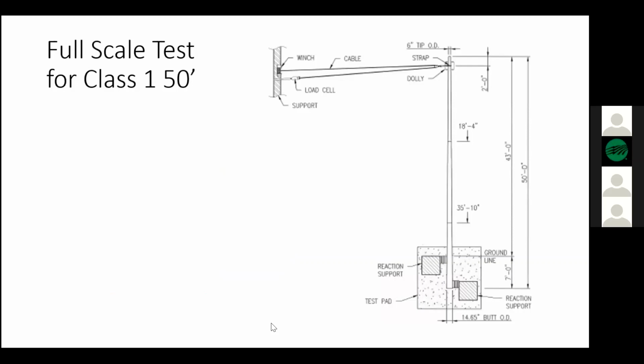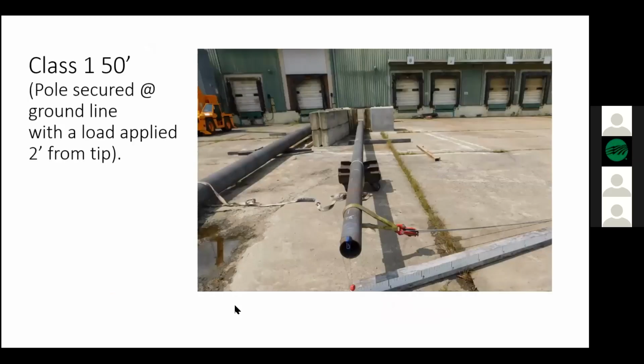Load testing. Here's a diagram of some tests we had down here a few years ago. This was a 50-foot class one that we tested. The diagram shows how at the base we fixed the pole, and at the top we put a strap 2 feet from the tip where we applied load. I'll go to the next slide showing some photos of the actual test. Again, base is fixed, strap was attached 2 feet from the tip, and then we apply load.